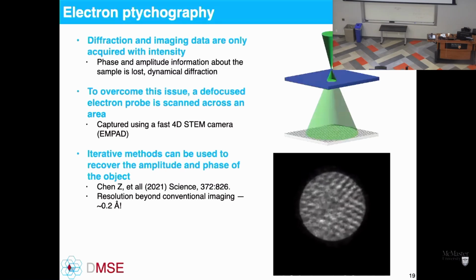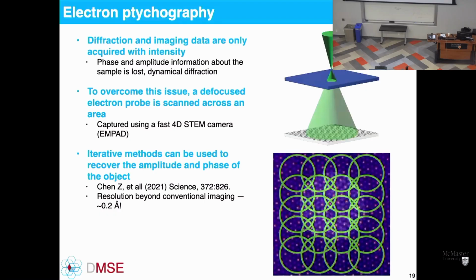So I know that those probe positions are connected by some phase ramp applied to my probe that is being scanned across the sample. And essentially, that's all the information I actually need to recover what that object was and the incident electron probe. This is a very highly redundant data set with a lot of overlap. So there are a lot of variables in this, but I also have a lot of data to solve for all of those variables as a consequence. And so from that overlap information and from iterative reconstruction methods, we can recover the object amplitude, the object phase, and recover the probe phase as well.